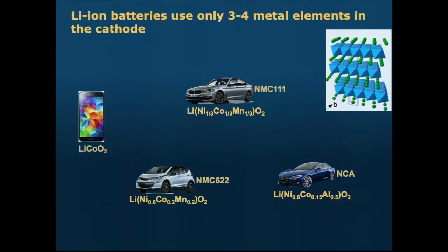So if you look at what's in your phone, it's pure lithium cobalt oxide still, right? It's the densest material, and if you're Apple, you care about shaving a tenth of a millimeter off the thickness of your laptop, which is crazy, but that's why they go for super high energy density. If you cut open your Apple laptop, which you shouldn't do, get a YouTube video, somebody's done this. Your laptop is not a laptop, it's a battery carrier, right? Two-thirds of the space inside your laptop is taken up by battery. It's not a single battery anymore, it's in many different pockets. So it's all about energy by volume, and lithium cobalt oxide is the pure winner there.